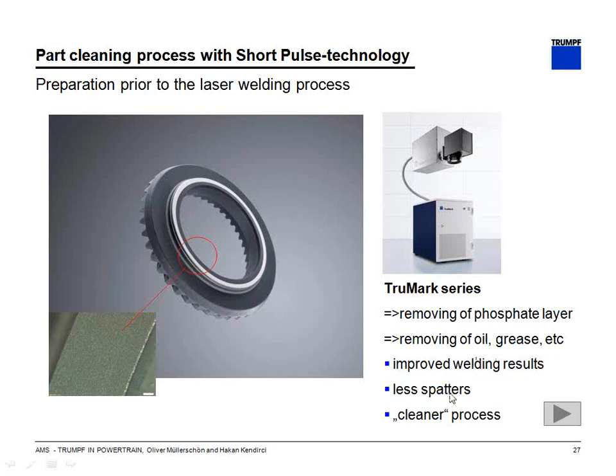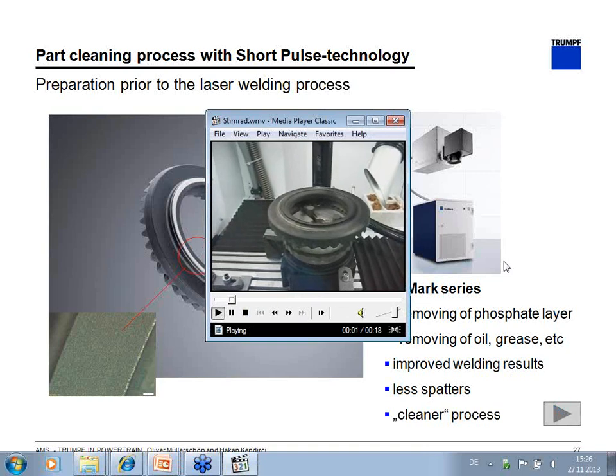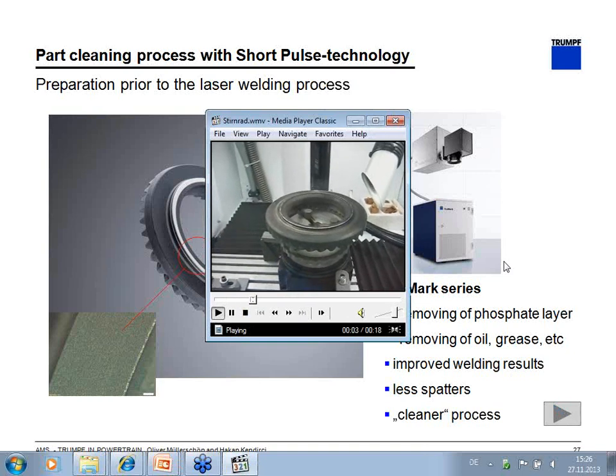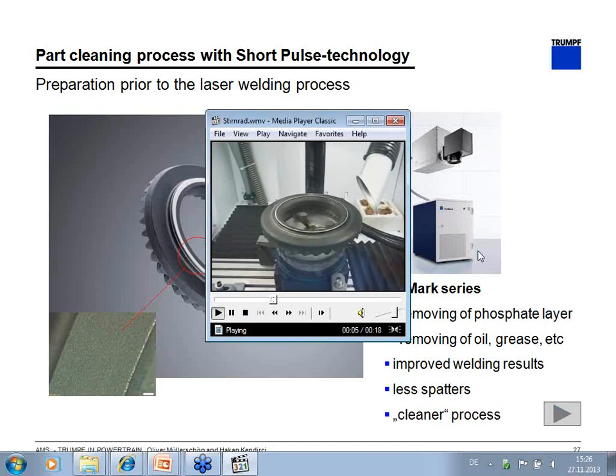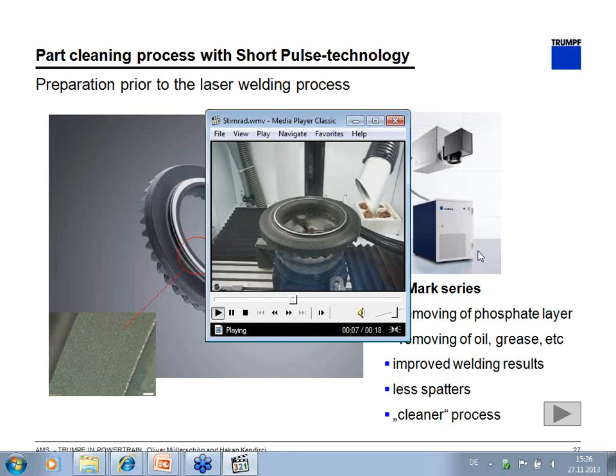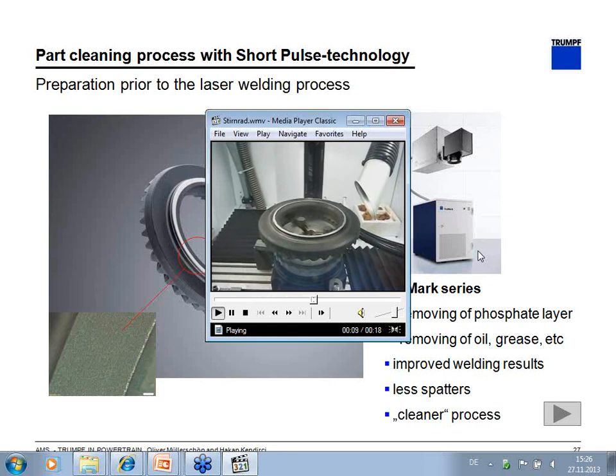This improves the welding result itself, so that means we have less spatters, we have a completely cleaner process. Just to give you an idea, this movie is made in our lab here. It's the ring gear. You can see this black colored surface, or layer. This is a phosphate layer in this example. And as you can see, within a few seconds we can remove it completely from the surface.